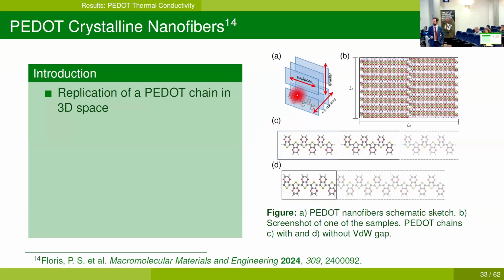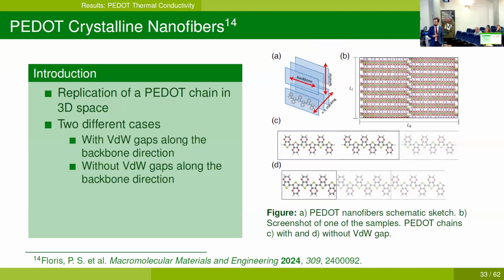So you can see it in the scheme here. We take one chain and we replicate it in space in all 3 directions of space, pi stacking, lamellar, and backbone, until we have something that looks like this in panel B. So very different from what we saw before. And we have to differentiate between 2 cases here as well. The 2 cases are depicted in panel C here and panel D.